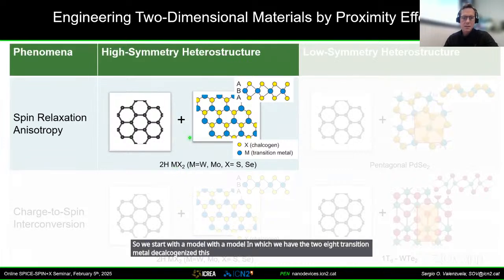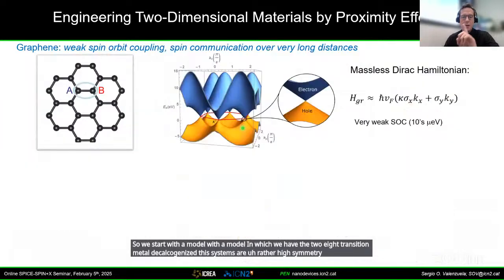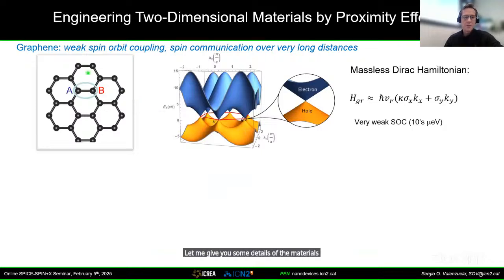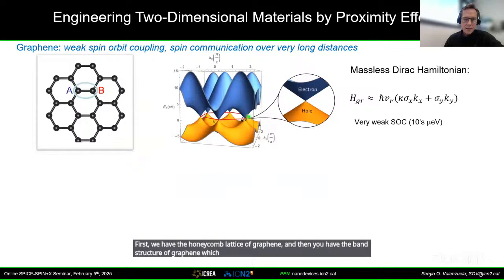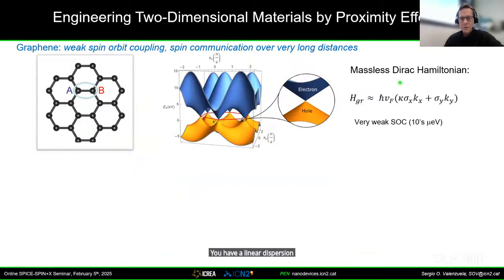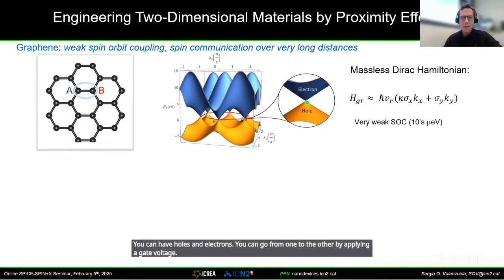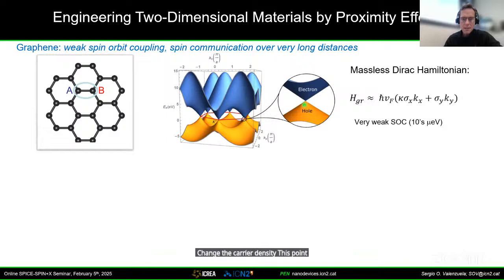These systems are rather high symmetry systems in a sense. So let me give you some details of the materials that we use. First, we have the honeycomb lattice of graphene, and then you have the band structure of graphene, which has states in the K and K prime points. You have a linear dispersion relation, a description with the massless Dirac Hamiltonian. You can have holes and electrons. You can go from one to the other by applying a gate voltage, changing the carrier density. This point here is the charge neutrality point.